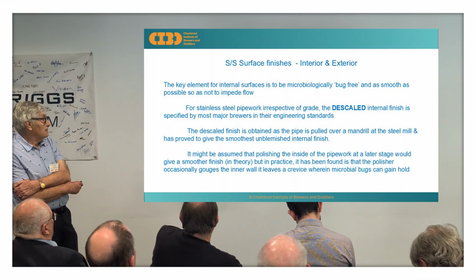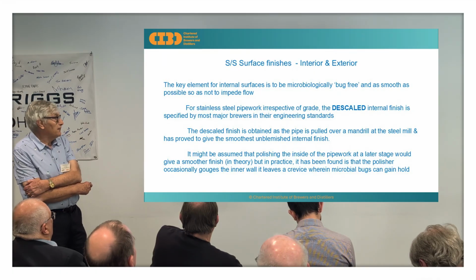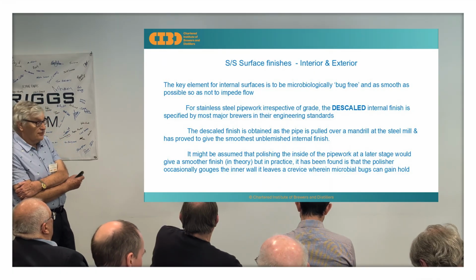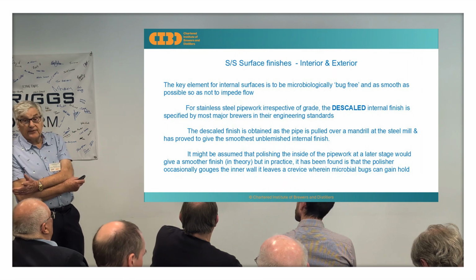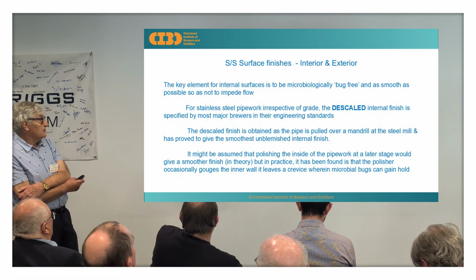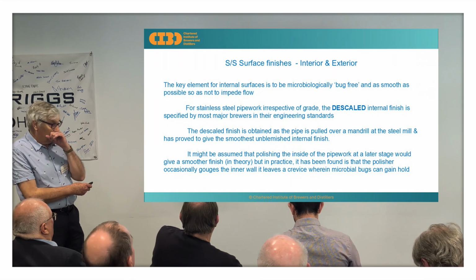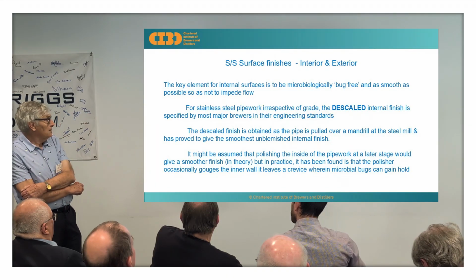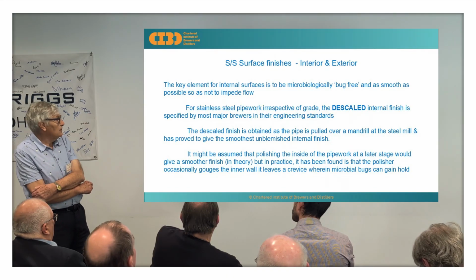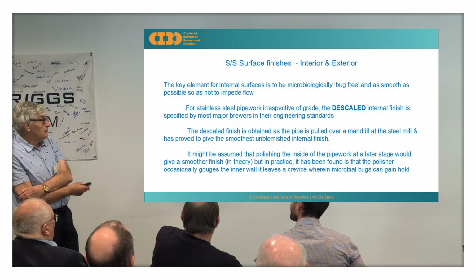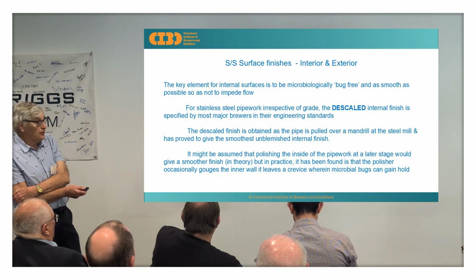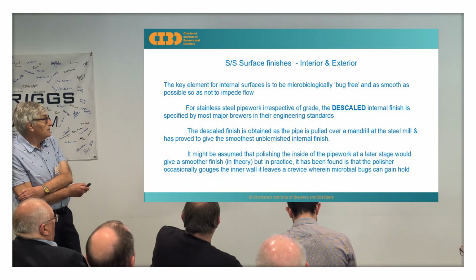You'd think that polishing the inside of the pipework at a later stage would give a smoother finish. Well, it would in theory, but in practice it's been found that the polisher occasionally takes a gouge at the inner wall. This leaves a crevice, which is then where bugs can set up home.